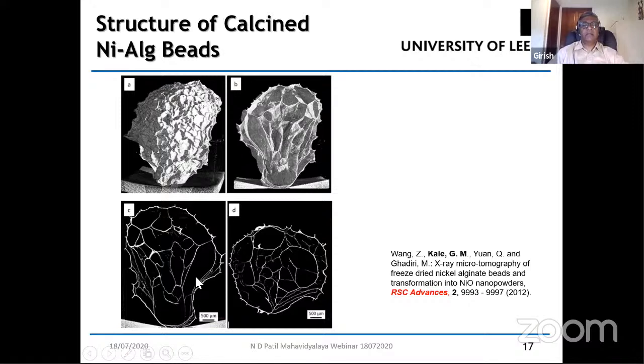Because these veins are widely separated from each other, during the calcination, what we believe is that even though we have to calcine these beads at about 500 degrees Celsius, because of the lack of diffusion path between these veins due to the presence of void, it is not possible for the grains to grow. Hence, it consistently produces nanoparticles. That is what happens in co-precipitated materials: because there is no empty space, the particles are in contact during calcination, and therefore it is hard to get nanopowders consistently.